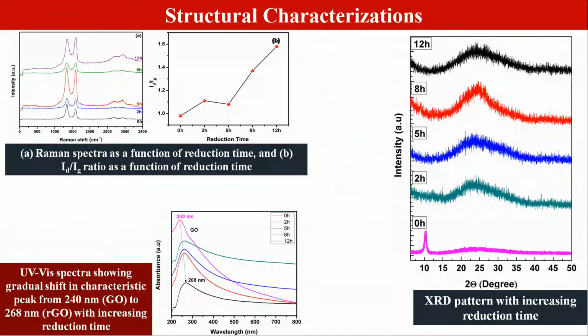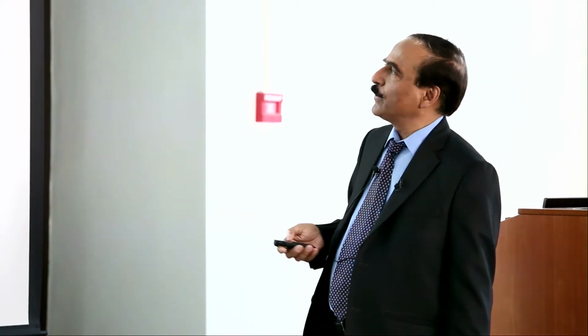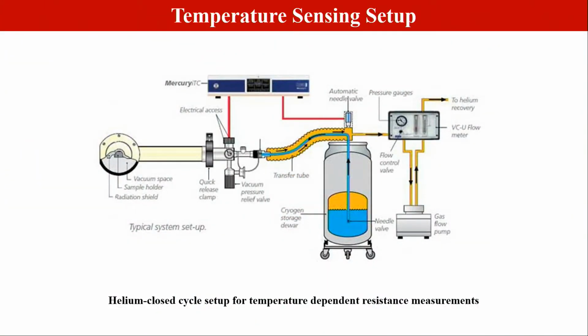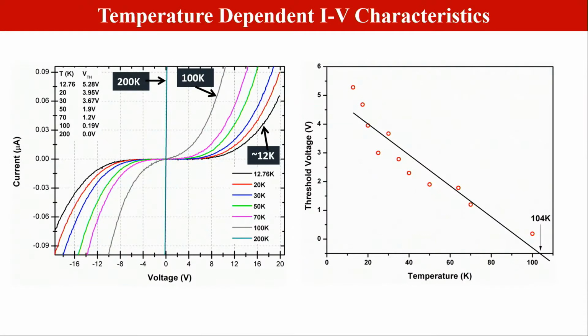Also, in the UV-visible spectra, this is the graphene oxide, when the functional groups are there; when they are removed, we are moving towards the graphene structure. This is for the thermal part. This is one low temperature study we will do. This is the temperature dependent IV characteristics, very important. We have a structure from 12 Kelvin to 100 Kelvin, even up to 200 Kelvin. We see in the lower temperature there is a threshold voltage region. In this region, as I showed, the quantum dots behave with a Coulomb blockade effect.